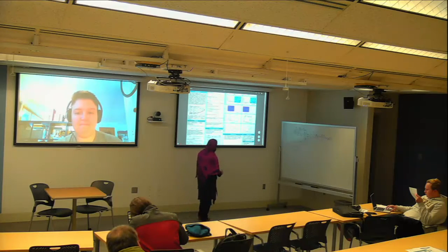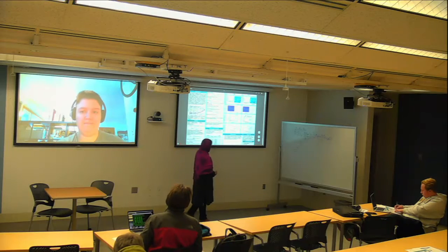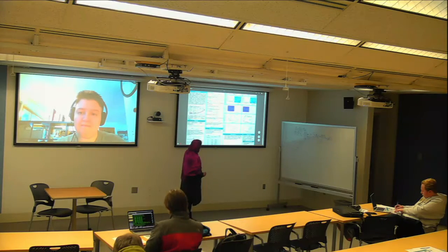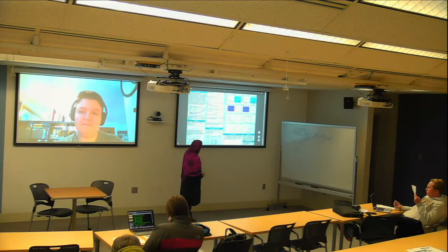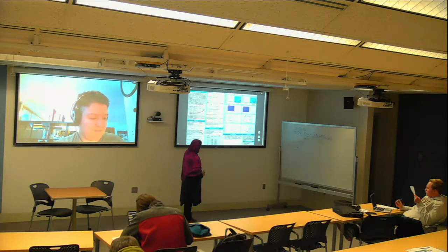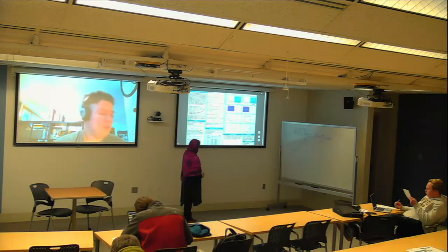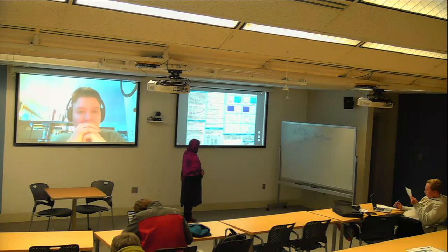So these above data are for momentum restricted, and these bottom filled symbols are for all transitions. And the same thing here: probably after fitting, I would say there are two regimes where the energy gap law is followed, and for the second part, I would say the inverse gap law is applicable. But I need to fit it first.